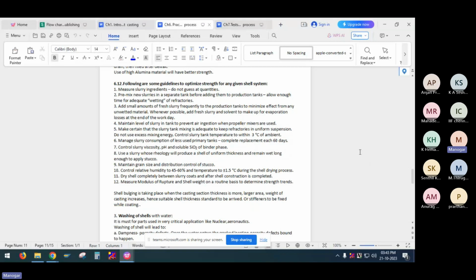Maintain the level of slurry in the tank to prevent air ingestion when propeller mixers are used. Make certain that the slurry tank mixing is adequate to keep refractories in uniform suspension. Do not use excess mixing energy. Control slurry tank temperature within 3 degrees centigrade. Manage slurry consumption of less used primary tanks. Complete replacement each 60 days. Change that slurry before 60 days. That is the suggested thing for better quality.